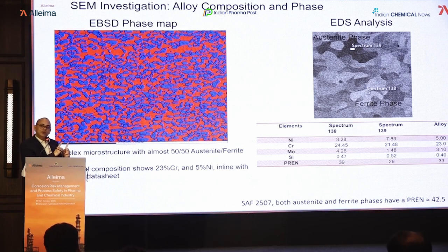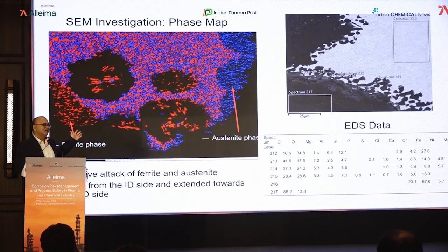So due to difference in chemistry, there is a difference in the PREN number, and if there is some aggressive environment, the one with the lesser PREN number will get attacked first. And what you could see here, in this region, the red is there, it means austenite is gone, that was expected. But there is something wrong in that region. Where we were expecting austenite will leach out, but here the ferrite basically gone.